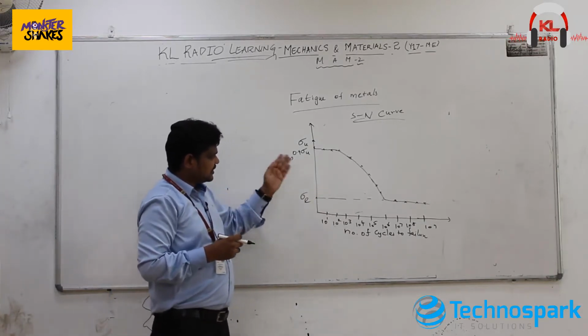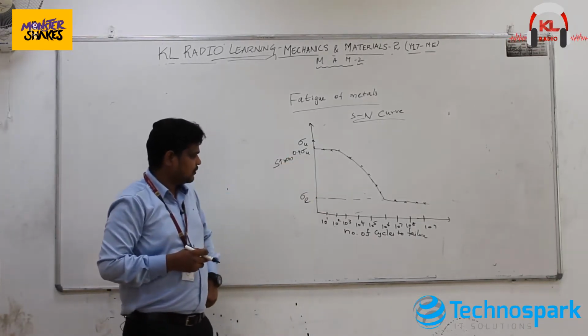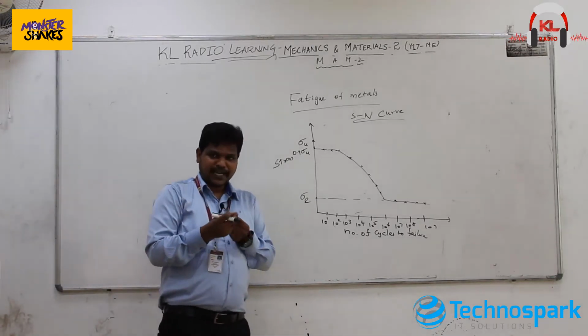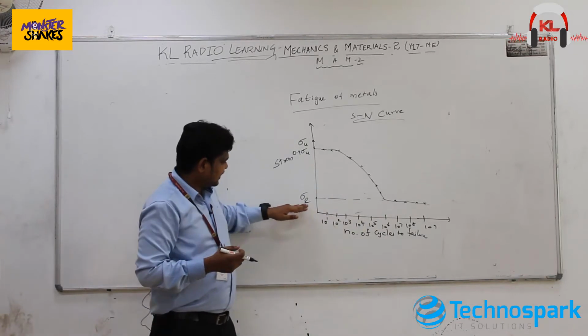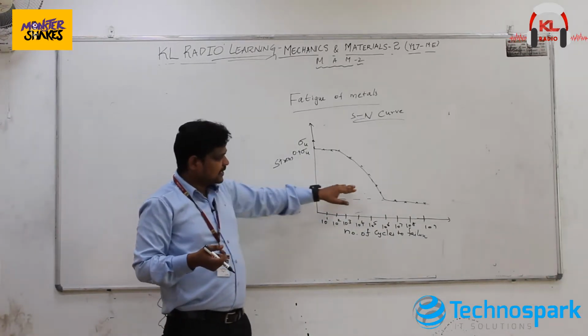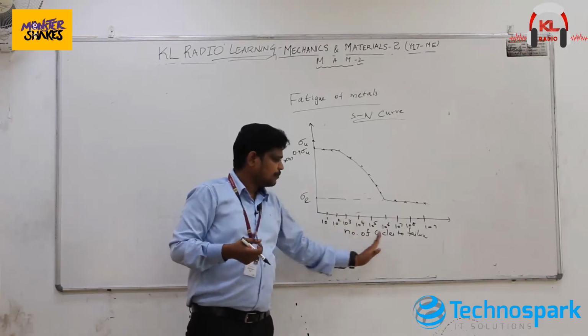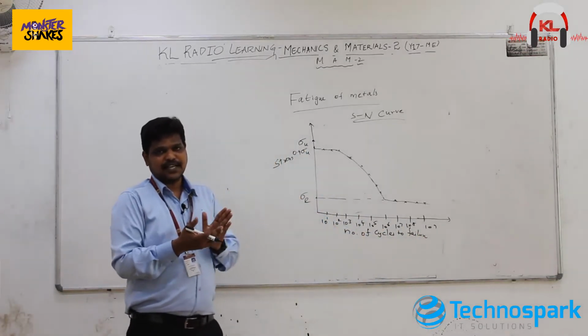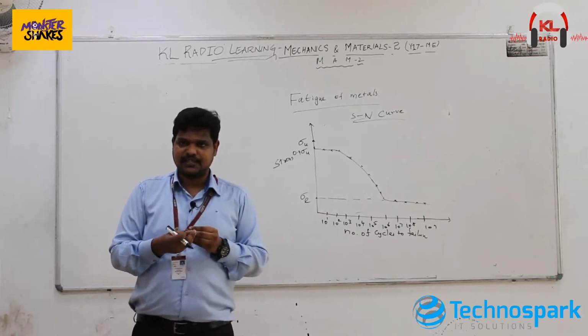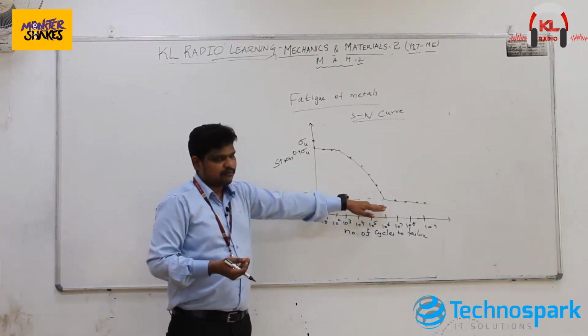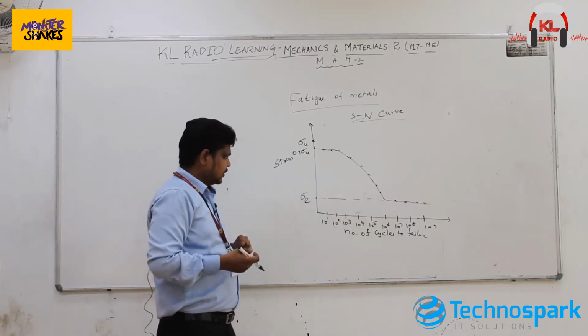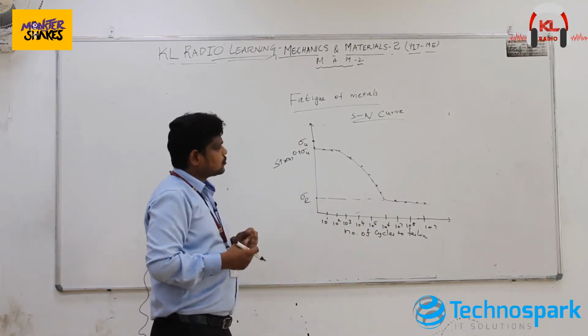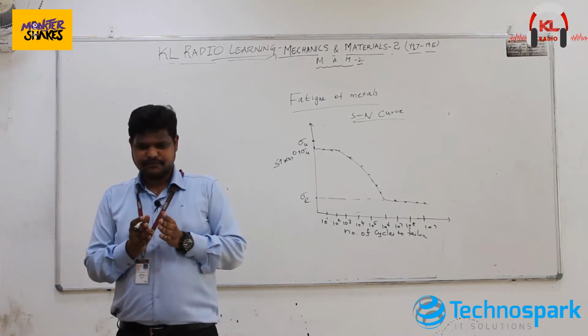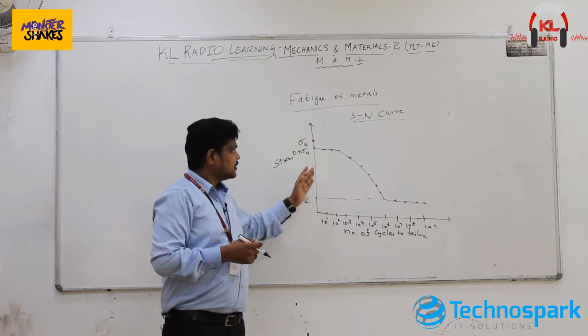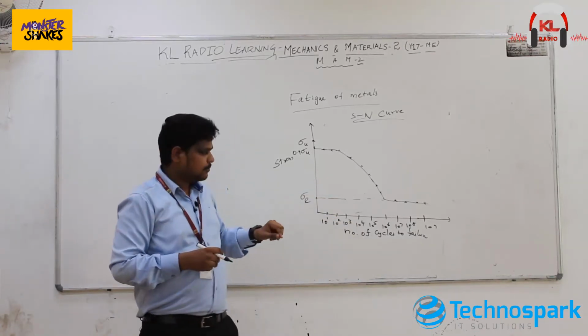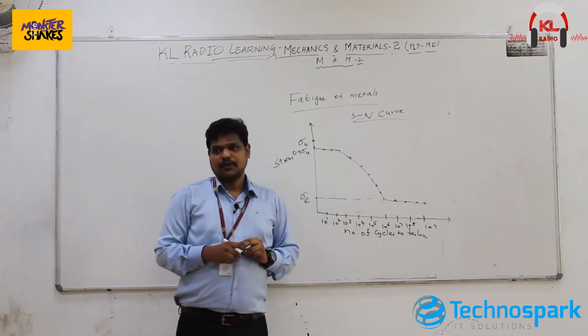Here, if you notice from the stress versus number of cycles to failure curve, if you maintain the stress on a metal at this endurance strength, then the material can withstand any number of cycles without failure. I mean to say that the metal will have an infinite number of cycles without failure if you maintain the stress level at its endurance limit or fatigue limit. Right. So the test will be conducted for various metals and we'll have various stress versus number of cycles to failure curves, and we will find the endurance limit of the material.